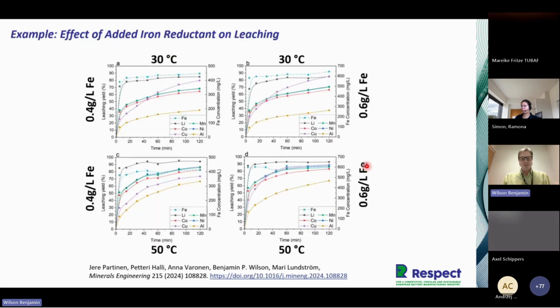So just a quick example, as we've not got a lot of time today. Just thinking about what we saw at 30 degrees without any reductants, the levels of leaching of the key metals were relatively low. But as you can see here, even at 30 degrees with the addition of iron reductant at 0.4 grams per litre or 0.6 grams per litre, there's been an increase in the leaching of the metals of interest, still relatively conservative, 50-60% for cobalt, for example, but this is still an improvement at a temperature of 30 degrees compared to without any reductant whatsoever.